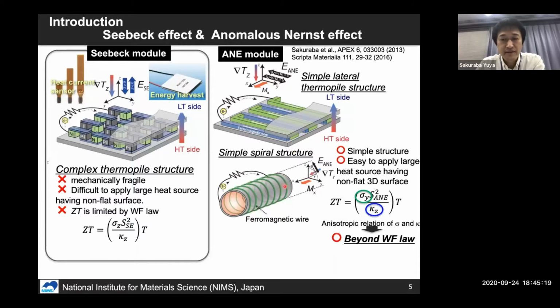And when we use this kind of three-dimensional shape heat source, such as this tube shape heat source, we don't need to make the thermopile structure anymore. We just need to roll one ferromagnetic wire in a spiral. In this structure, the electric field of the anomalous Nernst effect appears in the tangential direction. Therefore, we can easily obtain a high serial output voltage depending on the total length of the ferromagnetic wire. And when we see the expression of ZT, we can notice that sigma and kappa appear in the perpendicular direction. So if the magnetic material has anisotropic material properties, we can control ZT beyond the limitation of the Wiedemann-Franz law. That is another important advantage.